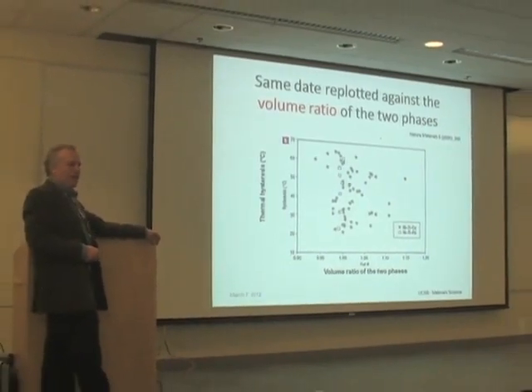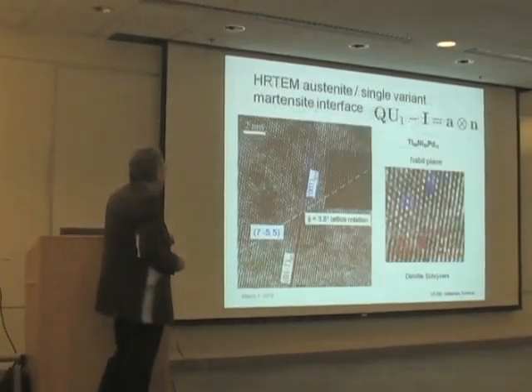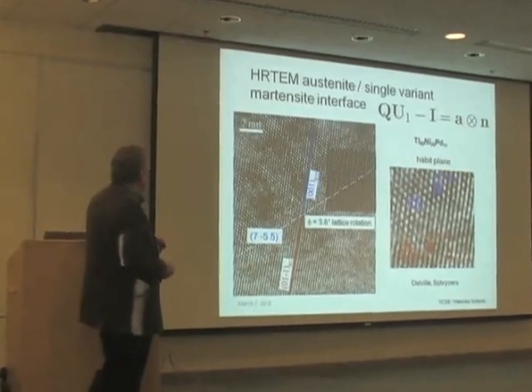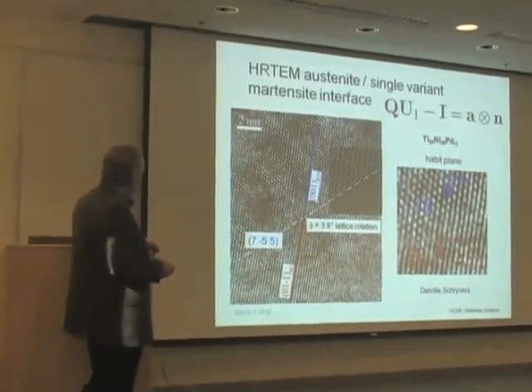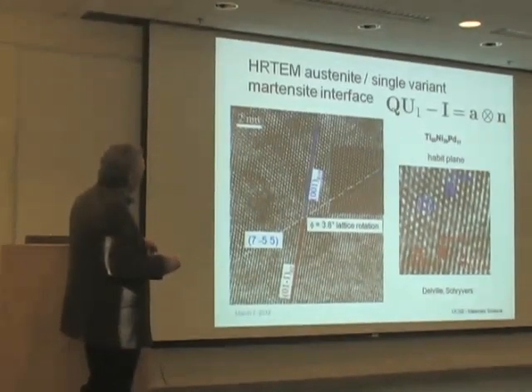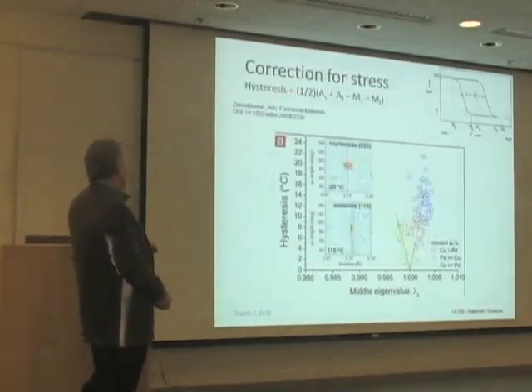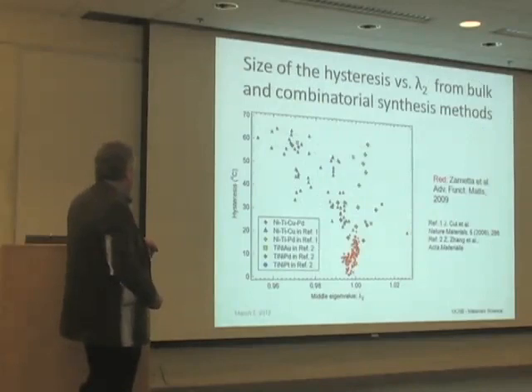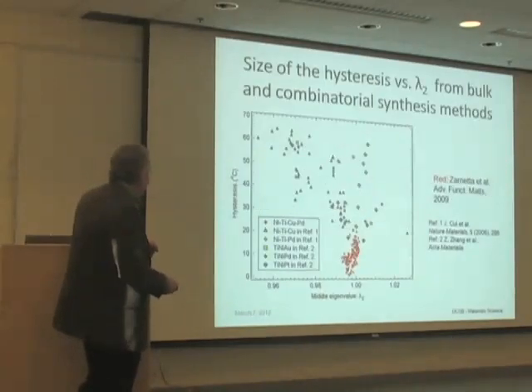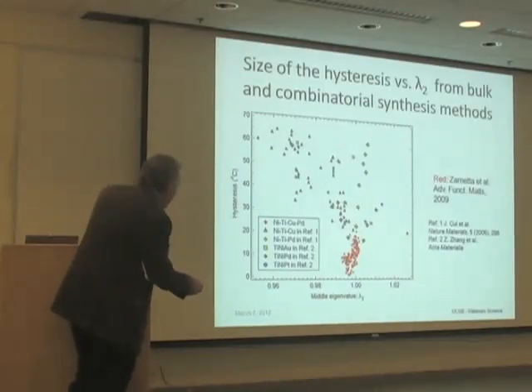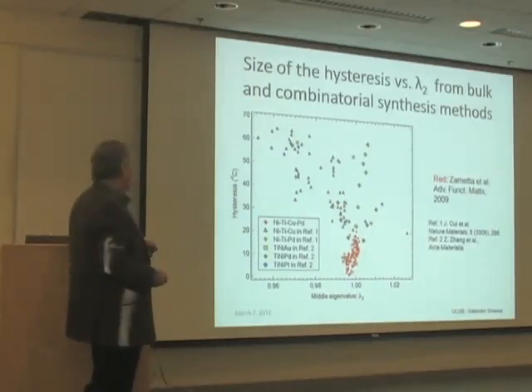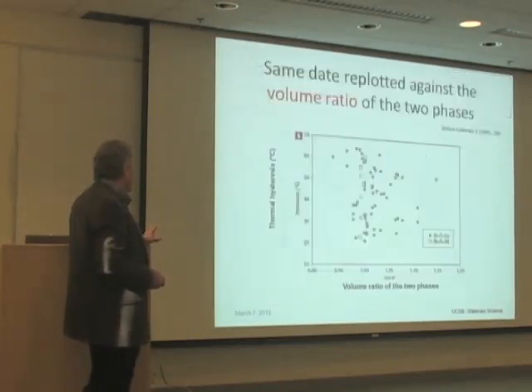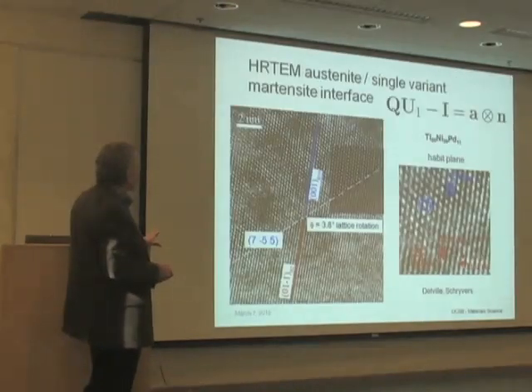Okay, here's a picture, a TEM picture, of an alloy which is tuned to have lambda 2 equals 1. Actually, it's not quite lambda 2 equals 1, because, okay, it's a funny thing, this is evolution in our thinking. So that alloy is actually right there, and it's about 14 degrees hysteresis or something. And we used to think, and that's 11 in this system, this titanium nickel palladium, that was the lambda 2 equals 1 alloy because of that previous graph.